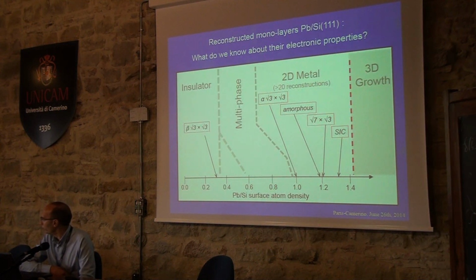Next slide, please. In fact, this is the phase diagram of this monolayer of lead, so you have just a single layer of lead atoms. The metallic phase is situated between 1.0 and 1.4 atoms of lead density as related to silicon density. So at low coverages on the left part of this diagram, you have insulating phases. So you have lead atoms, but they do not percolate and there is no metallic conductivity. But at densities above one single monolayer, you have different phases which are shown here, and all of them are metallic, and some of them are superconducting.